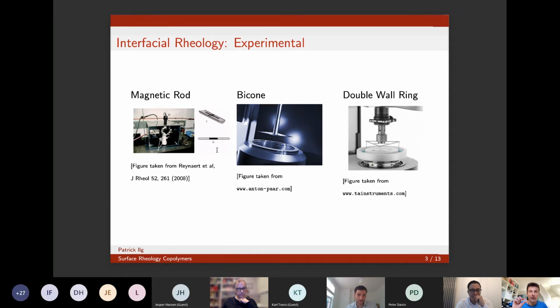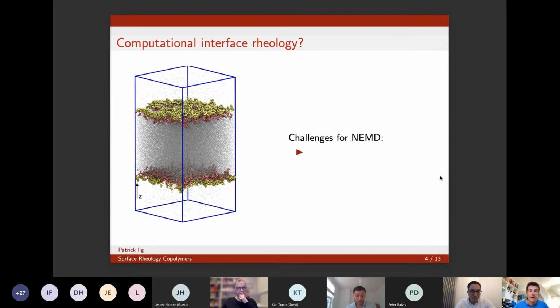So you have a bicone with a tiny, tiny opening angle. You want to place it right at the interface, and then just do a rotational rheometry on the interface. This is also commercially available now from Anton Paar, and a double wall ring experiment where you're trying to do the same, but you have a better defined flow because you have these double wall rings. Anyway, the message here is that it's new, and experimentalists are still more or less trying to figure out how to do it best. In simulation, we have, of course, way more freedom, so maybe we can do it better or easier.